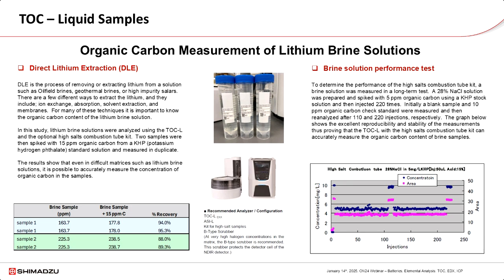As you can imagine, brine solutions can be very tough on the instrument, especially for the combustion tube and the consumable items such as the syringe, valve, and scrubbers. For this test, a 28% sodium chloride brine solution was prepared and then spiked with 5 ppm organic carbon and measured 220 times by the instrument.